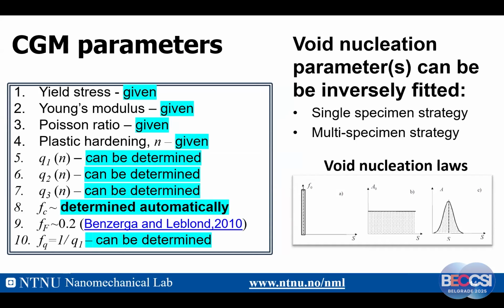Then we can analyze the parameters involved in CGM. In CGM, we have yield stress sigma zero, Young's modulus, and Poisson ratio, which are given, and plastic strain, also given. Then we have Q1, Q2, and Q3. In principle, these can be fitted very nicely as a function of the hardening exponent N. With machine learning techniques, we can have a perfect fitting of this.